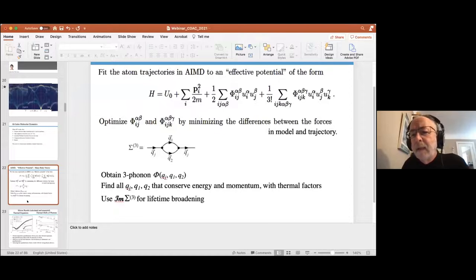Both the ab initio calculation, which we call TDEP, and the ARCS data are in agreement, and also at some arbitrary point in the reciprocal lattice. We've looked at a few hundred phonons in the Brillouin zone, and 85% of them are incorrect with the sign of the change predicted by the quasi-harmonic approximation, which depends on volume alone. The annoying thing is that the quasi-harmonic approximation gets the thermal expansion of silicon about right. And assuming this negative Grüneisen parameter for the low transverse modes seems to kind of work.